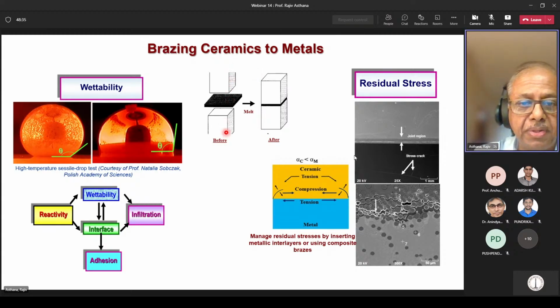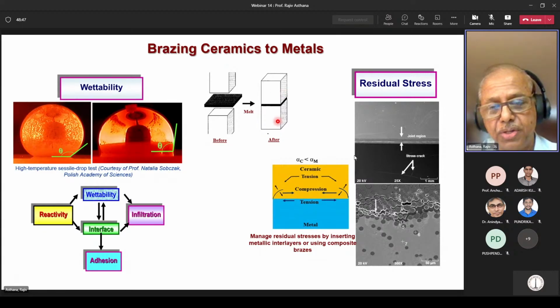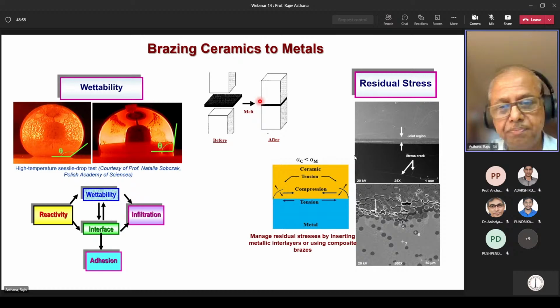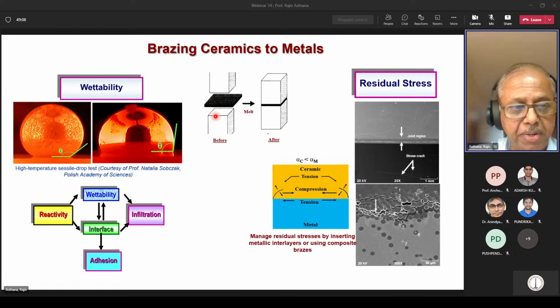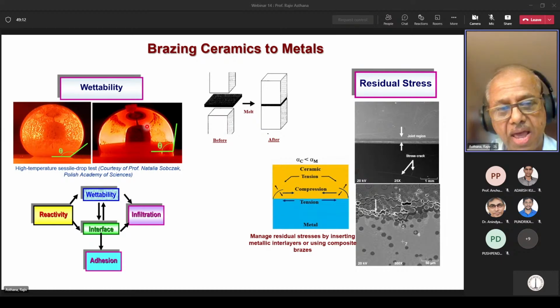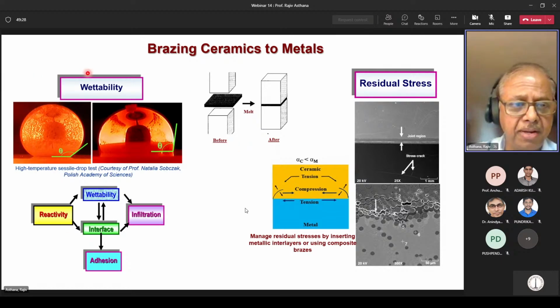The concept in brazing is very simple. You take a joining material, which is basically some sort of glue, metallic or glassy, and you melt it and then bring the two surfaces together under a very small pressure. The melted braze will spread over the surfaces, and upon cooling, the surfaces should bond. Two key areas in this kind of process are, first, wettability, that is, the liquid should be able to spread and bond to the surfaces. And then, because of expansion mismatch between the surfaces, there is quite often a lot of residual stress that has to be managed in some way or other. So in my talk today, I'm going to look mainly at the wettability part in high temperature systems.